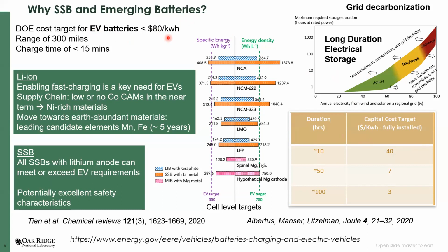In the US, people drive quite a bit and they drive long distances. So the batteries that we want in a place like the US should have a range of about 300 miles. So it's somewhat comparable to what we get out of a gasoline internal combustion engine based vehicle. Furthermore, when we go to fill up our gas, we normally can do it in 5 to 10 minutes. So a reasonable charge time for an EV battery should be of the order of 15 minutes or less. So these are quite demanding metrics that have to be reached in batteries. So we have to enable fast charging.